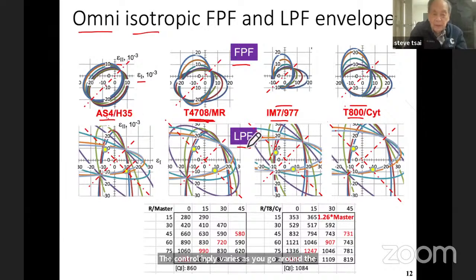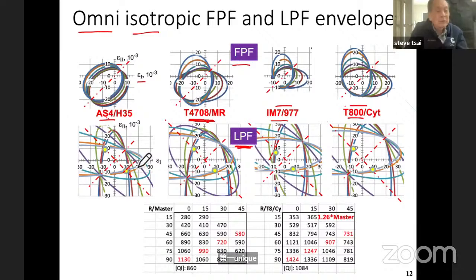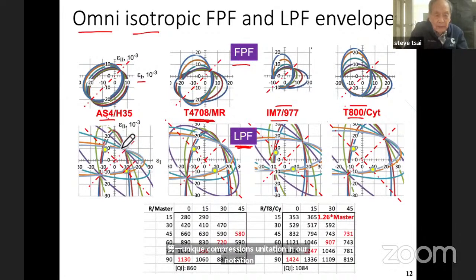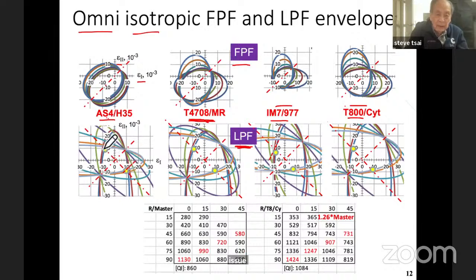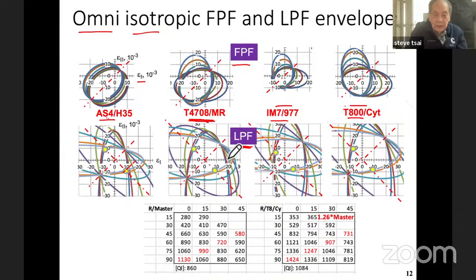For the last ply failure — which is really the ultimate — you only need to know the uniaxial tension and uniaxial compression, X and X prime. This being isotropic space, you can find out what the shear strength is: shear strength will be at 45 degrees — along minus 45 degrees, where tension and compression are equal. So in the last ply failure envelope, we know the zero tension, zero compression, and the shear at 45 degrees. The circles here represent the shear strength.